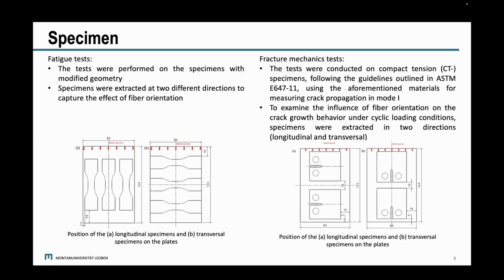The specimens for fracture mechanic tests are extracted from the injection molded plates according to the ASTM E647. Also in two different directions. Once we have the longitudinal direction, in which the fibers are mostly perpendicular to the direction of crack growth, and in transversal direction, in which the fibers are mostly parallel to the direction of crack growth.